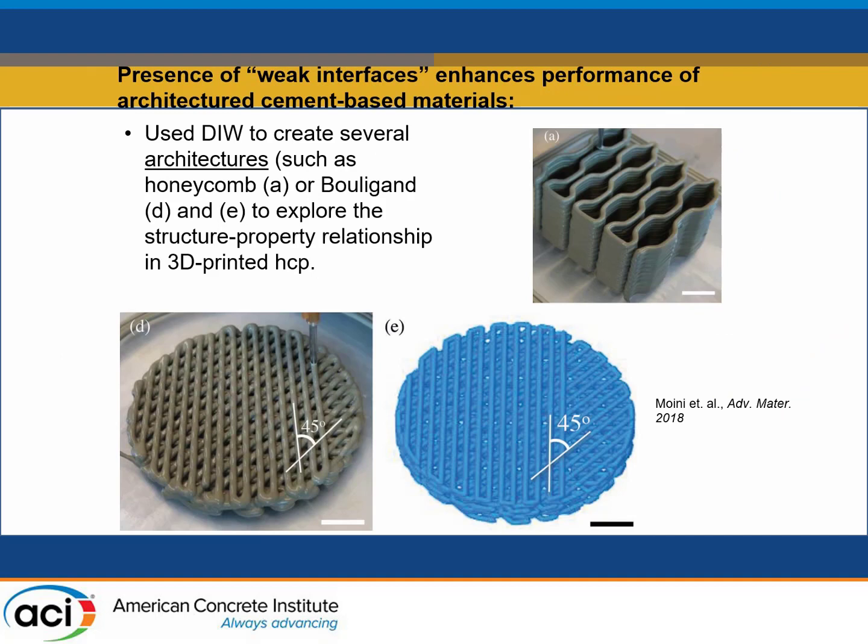So one of the things that we've done is we created various types of concrete elements with different internal architecture, right? So this is a honeycomb kind of structure. Actually, this acts like a spring. I couldn't make the video link work in here, but if you squeeze it, it actually deforms elastically and bounces back. So you can think of it as a sort of concrete spring. No reinforcement, but it doesn't break.